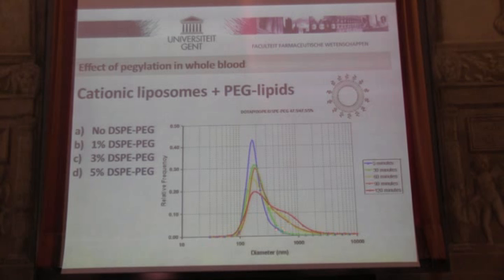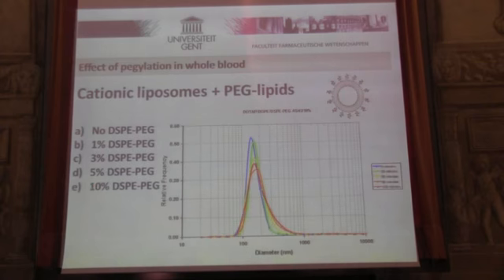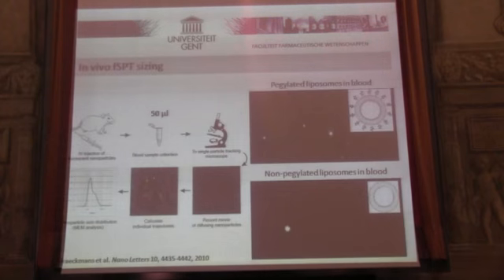You see, there's still aggregation, but it's already much less, as you can appreciate. But only from 10%, we could keep these liposomes stable in blood for at least 2 hours in this system. So 10% is the least amount, according to our finding, that should be included. And then we went on to an in vivo experiment where we injected these pegylated and non-pegylated liposomes to see what happens in vivo. We inject the rat.